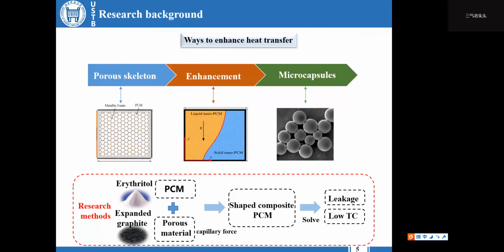For energy storage systems, improving the thermal conductivity of phase-changing materials is the key to enhancing the thermal response characteristics. There are three methods for enhancing the heat exchange of phase-changing materials: encapsulation with a high thermal conductivity porous skeleton, adding high thermal conductivity enhancers, and using microcapsules with high thermal conductivity material as shell material. The use of porous material encapsulation has the advantages of simple preparation process, low cost, good compatibility, and good cycle stability. The porous skeleton uses capillary force to encapsulate the phase-changing material, which has a three-dimensional interconnected thermal conduction path, which can improve the thermal conductivity of the phase-changing materials.